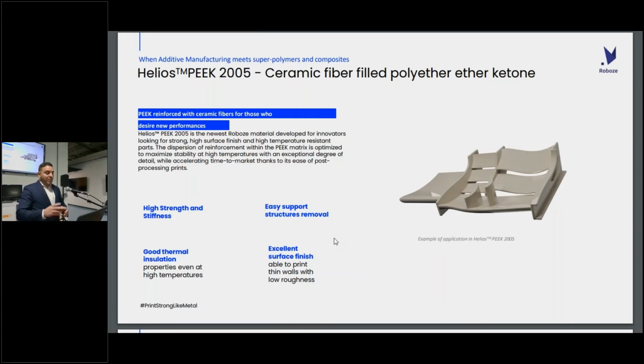The material has about 40% more strength and stiffness than PEEK. There are very specific ceramic fibers that we develop with this material. Why? Because when you have a composite material, there is always a kind of delamination from the fiber structure to the polymer structure. That increases the porosity, which gives external agents, whether temperature or chemicals, more space to go inside that part and break the polymer chain.